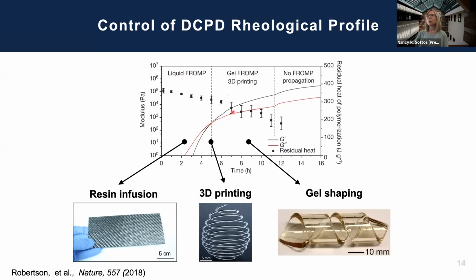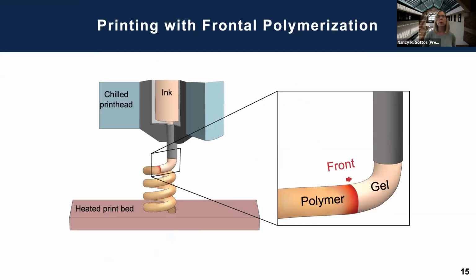If we let it go beyond the gel point, and this was actually a very surprising fact to us, we can go beyond the gel point and there's still enough energy to frontally polymerize, and it enables us to process from the gel and do things like 3D printing and gel shaping, as you see here. And then finally, if it goes too far beyond the pot life, a background reaction will take over. It'll polymerize into an undesirable polymer, and you just don't have enough heat of reaction to propagate the front. So you want to stay away from that zone. Before I get into composites, I just wanted to show two examples of how we use this material to print.